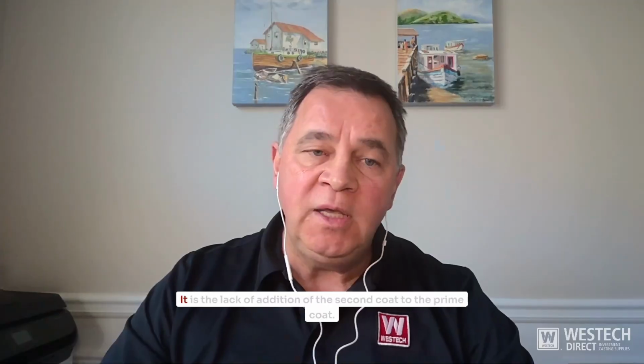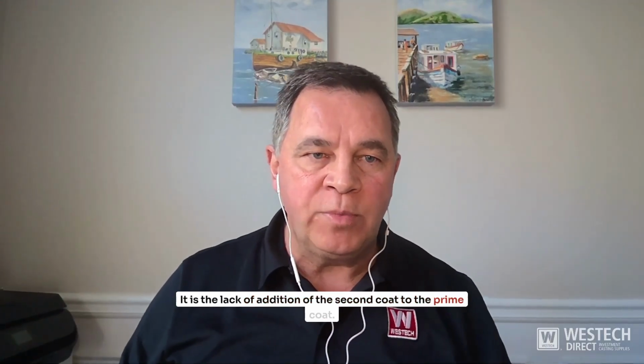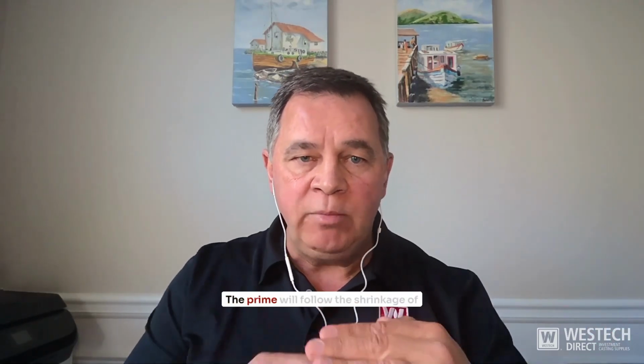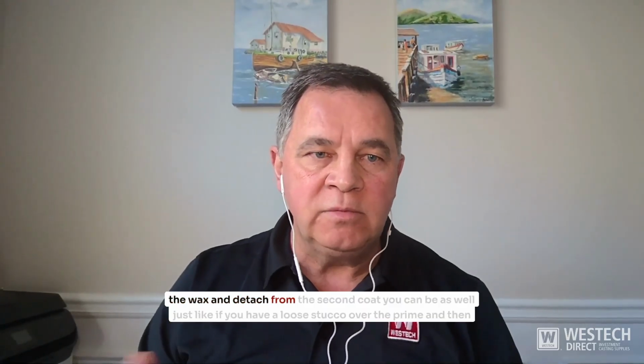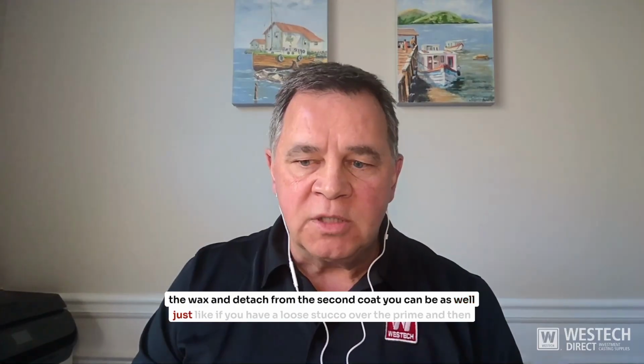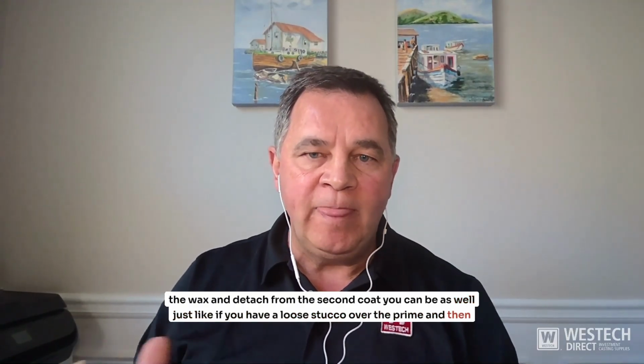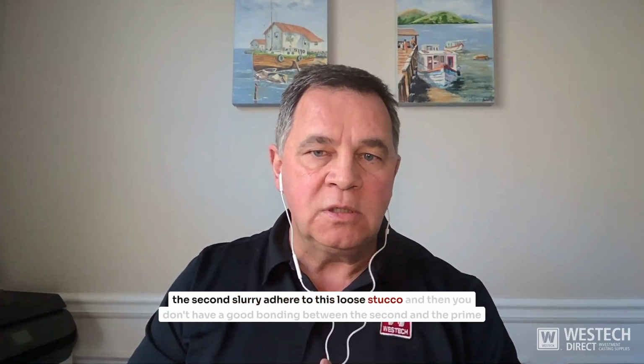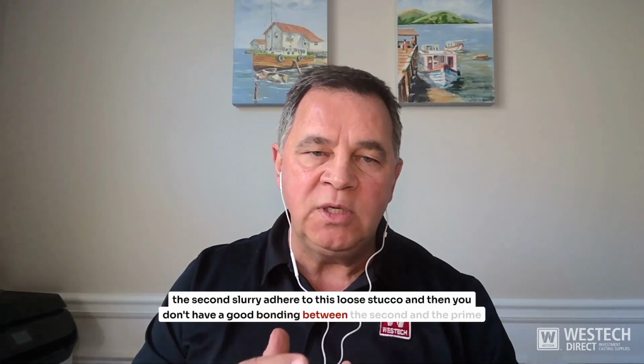First of all, spalling is one of the worst defects in precision investment casting because it can come from all kinds of different sources. It is the lack of adhesion of the second coat to the prime coat. It can be, for example, room temperature excursions. While drying, the wax will shrink, and the prime will follow the shrinkage of the wax and detach from the second coat. It can also be a loose stucco over the prime, and then the second slurry adheres to this loose stucco, and you don't have a good bonding between the second and the prime coat. So it is not an easy defect to solve. It is a detective job, and we can help with this kind of defect. It is one of the worst, I can tell.